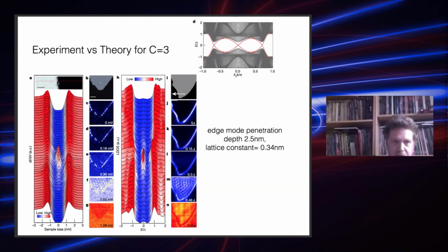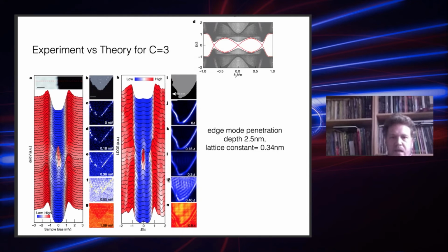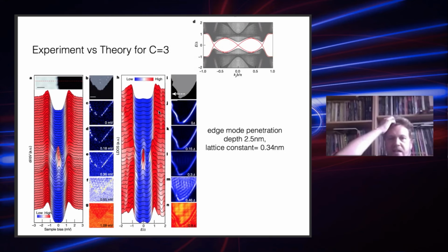So when you are at the boundary, you see this edge mode enhancement, or something that we think would be the edge mode enhancement. And when you move into the clean system, then this disappears. This is the experimental data that you see. And here is our simulation data based on the model here. Basically you see that the simulation results are qualitatively very well in line with experimental findings.